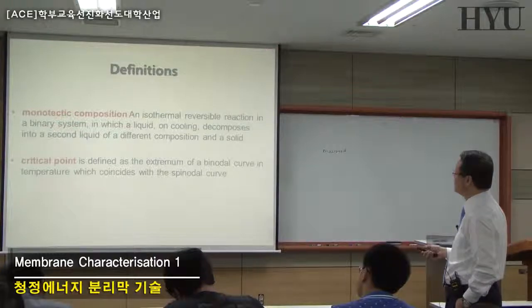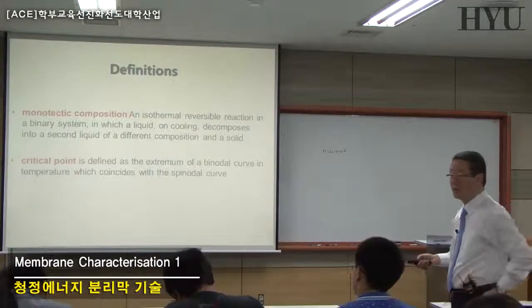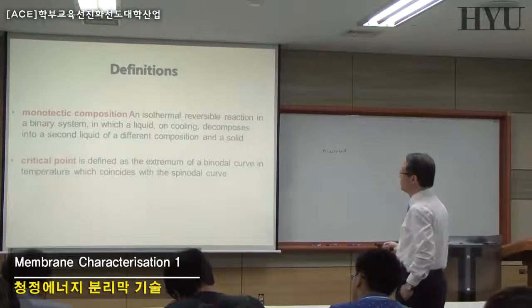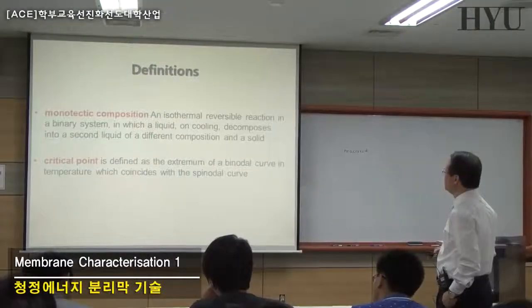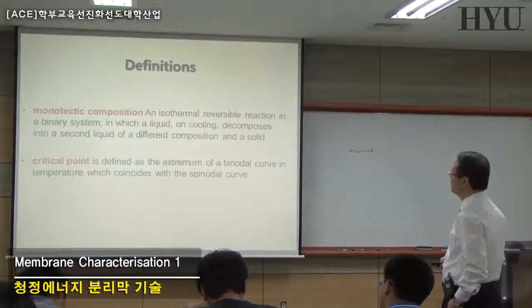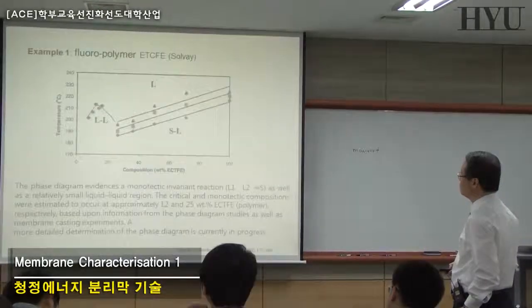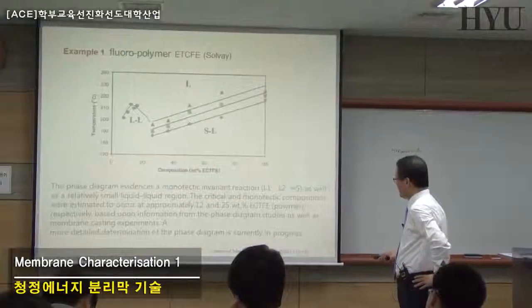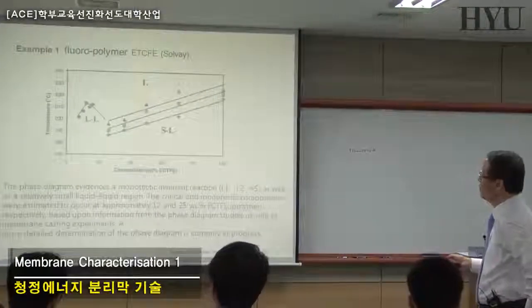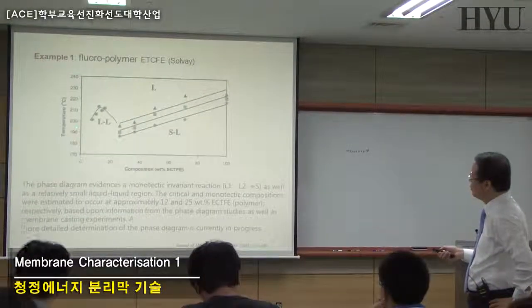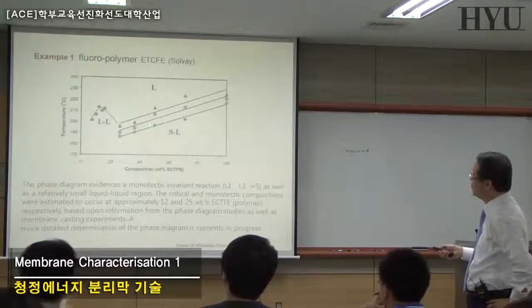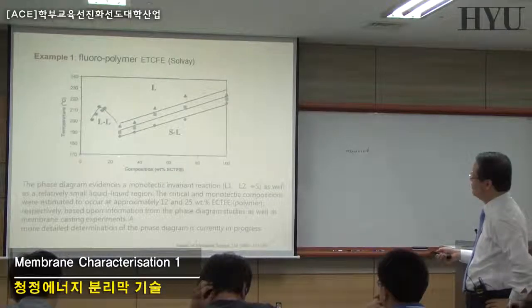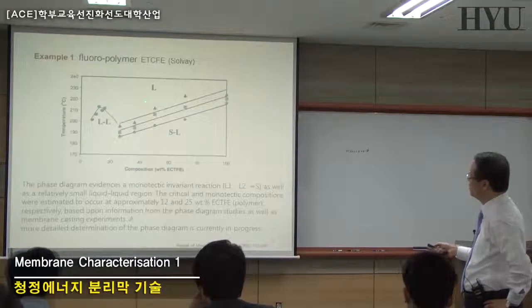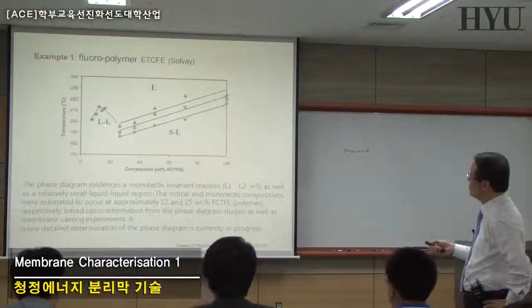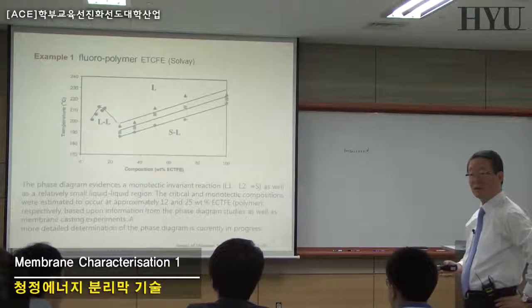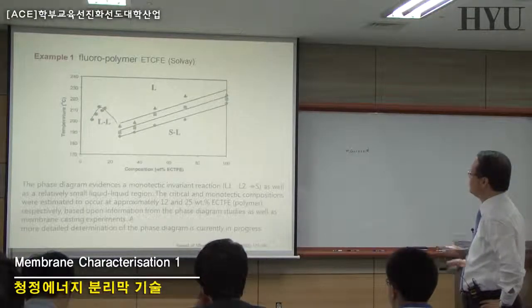I think we have described it here. The monotectic point or monotectic composition is important because it could separate the liquid-to-solid phases. In the literature, you can find many of this type of phase diagrams, where the cloud points and crystal points meet together. This is the monotectic composition, and above this monotectic composition, you have a liquid phase. We have a solid phase or liquid phase here. So you can pass this liquid-to-solid phase separation by using this ECTFE polymer.